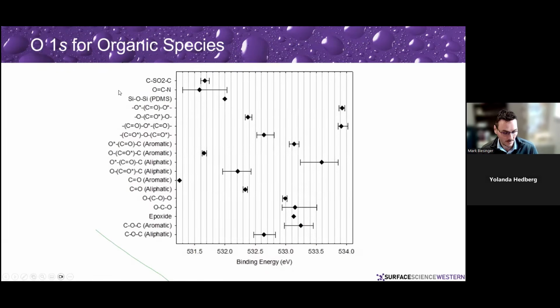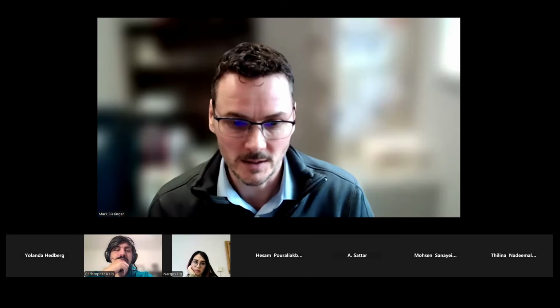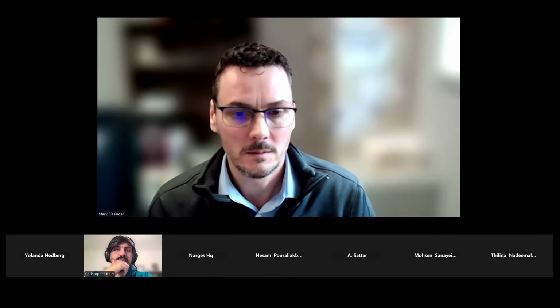So we've been looking at nickel for a long, long time. We've made nickel-3 species that we've analyzed in order to get those standard spectra. To see nickel-3 in the real world is actually pretty rare, a lot rarer than what you would see in some of the literature. And what happens is, let me go back to my screen here, and I'm going to go back to our nickel spectra.